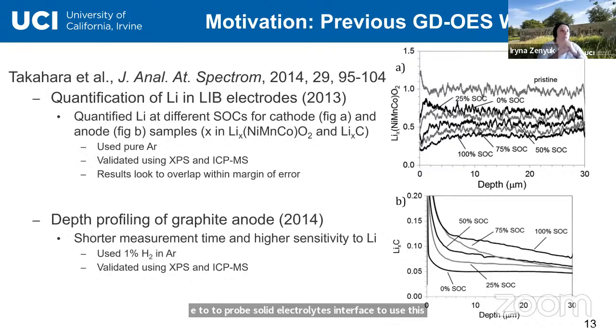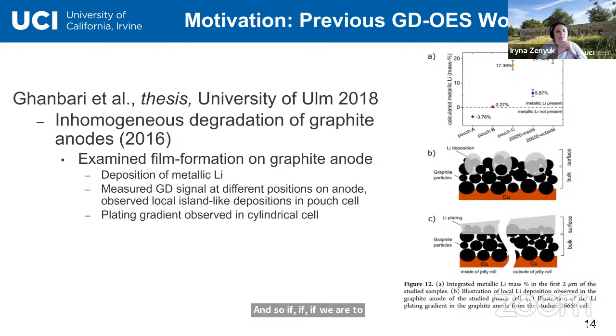If we look at another group that works in this domain, you can see that they probed lithium metal plating on the anode in the lithium-ion battery, and they were able to quantify the amount of lithium deposited. This is a destructive process, but one can actually extract the separator and the anode together and sputter away both the separator material and the anode if one is looking into that interface, for example. So it's all possible to look into those buried interfaces. That's what's been done before.